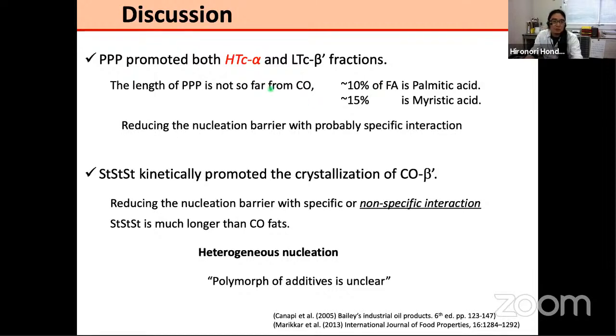And then especially the high Tc alpha should consist of the high melting fraction triacylglycerols with longer fatty acids. So this PPP, tripalmitin, can promote the crystallization of the high Tc fractions. That's why the addition of the tripalmitin can promote the crystallization of the high Tc alpha. And tristearin kinetically promoted the crystallization of the coconut oil beta prime. CO beta prime is a more stable form, and